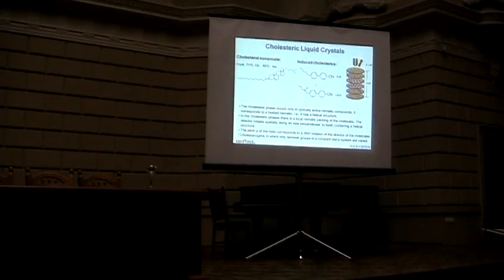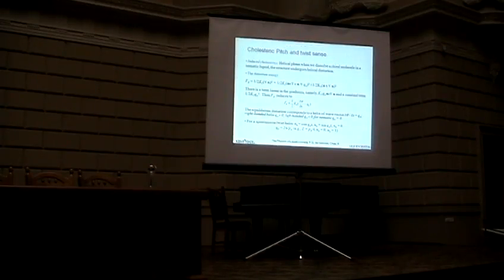and if this material is somewhat oriented in a plane with this director in one direction, and then by the surface control of the anisotropy, this material may adopt this kind of helical structure, and this helicity depends on the chirality of this dopant and the concentration of the dopant. So you can tune the helical pitch at your will. So if you choose to reflect in the wavelengths of light, in that case you can see the iridescent colors coming out from this material. If it's misaligned, then you can see multiple colors. This material normally has an angular dependence of this reflection.